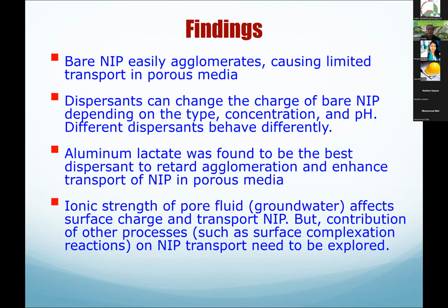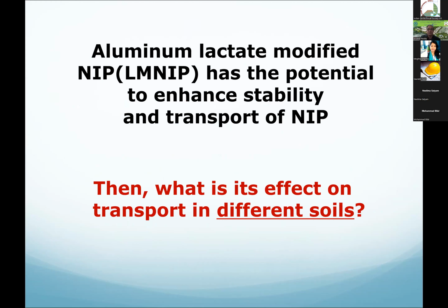And an important thing that we found in these experiments is that the pore fluid composition is extremely important. Groundwater ionic strength of the pore fluid affects the surface charge and transport of nanoiron particles, but other processes such as surface complexation reactions also contribute to the overall transport. So I hope I made it clear why we need a dispersant. And with this part of the study, we came up with aluminum lactate as the solution to the problem.